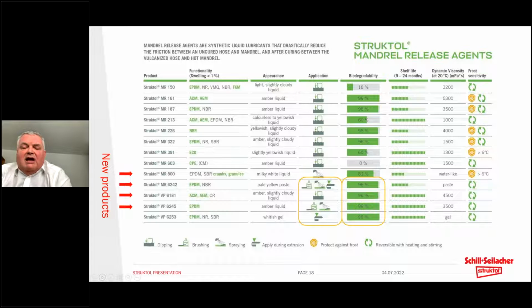Again, a product selector, and again, I don't want to go into details with products, except to say that it's very important to have products that are tuned to the polymer, the polarity of the polymer, so that they don't swell or penetrate into the polymer. They're not so compatible that they would damage the polymer in any way. Traditionally, conventionally, if you like, the application, the way of using such liquid-based lubricants is simply to dip the end of the hose into a bath and to push it around the mandrel.